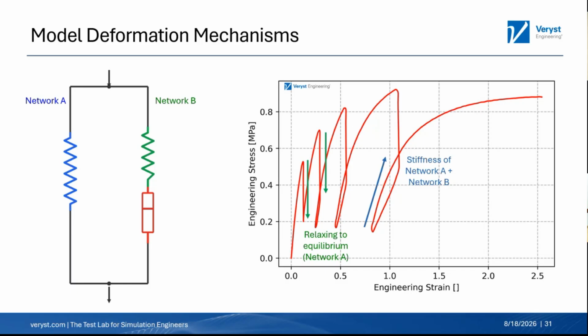And as we drop there, what's happening is we're going to an equilibrium condition where the dashpot is allowed to have some deformation over a very long time period, and then we're only going to have the stiffness of the A network. And so that's why we see that drop. And then we reload and we see the same drop here again at 25%. But as each one of those reloadings that we have, we're getting the stiffness of network A and network B again, where you can see that the slope here matches the slope here pretty well.